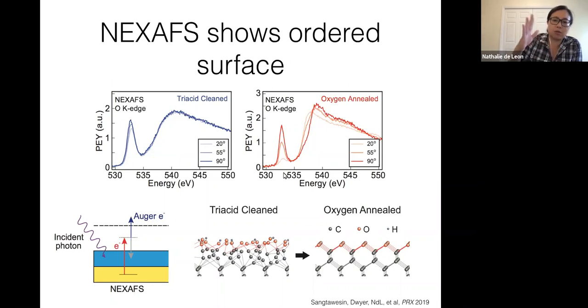So as I rotate the orientation of the sample relative to this polarized X-ray beam, you see that these features change drastically, whereas they don't for the acid clean surface. And what this indicates is that the bonds are highly ordered in this oxygen annealed surface, which is why you can actually see this polarization dependence.